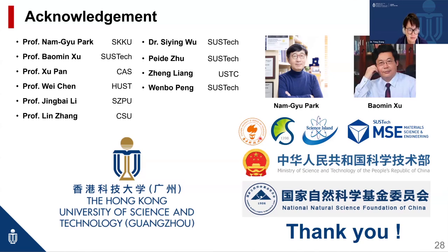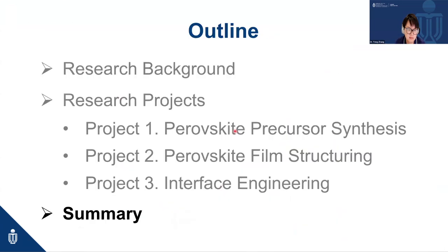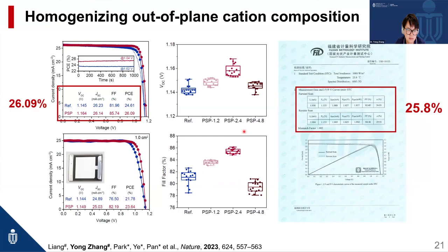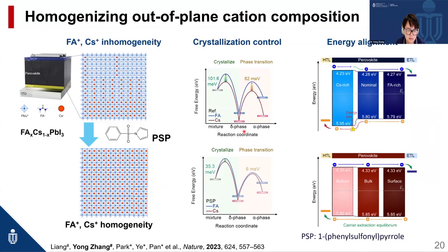For this inhomogeneity of Fa and Cs, right? I think that is very similar to halide segregation, but here your case is more like cation segregation. So in this situation, do you see it at normal conditions, or, for example, like halide segregation, we only see this under light illumination. For this Fa and Cs inhomogeneity, do you see it at normal conditions, room temperature, or in dark conditions, or what condition makes this case more serious?